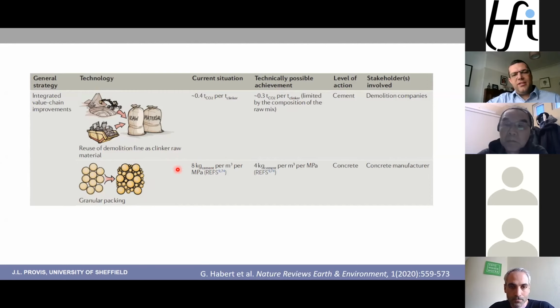So we look at, as a functional unit for concrete performance, how many kilograms of cement per cubic meter per megapascal of 28-day compressive strength. At the moment, 8 is about the figure we're looking at. Figures of 4 have been demonstrated. So we can get the same performance from the concrete in a normalized manner with half of the cement content by better packing the solid particles we're putting in there so that the aggregates packed together more tightly, still having a flowable material.